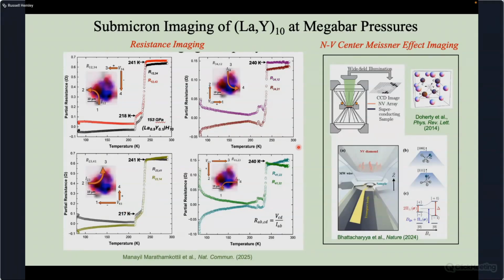These techniques are also being combined with another kind of imaging technique that we're working on. This builds on proposals we made several years ago that you could use NV centers for Meissner effect imaging, and this has been developed and refined by several groups, including this group at Harvard, where they've done some of the first work at megabar pressures using Meissner effect imaging. So now we're doing experiments. We're trying to combine the spatial diffraction imaging, the resistance imaging, with the NV center Meissner effect imaging, all in the same samples at the same time.